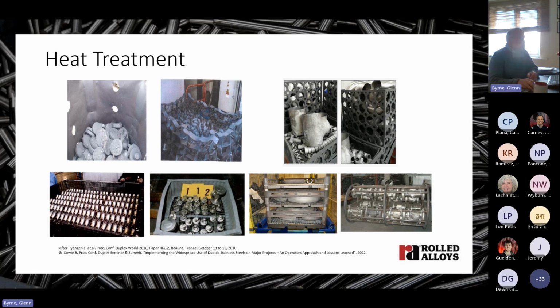Now, measurements using contact thermocouples in this particular case have shown that for parts in the middle of that basket, the proper soak temperatures and times are never achieved. The parts are heat treated in the temperature range where sigma forms and not where it dissolves.